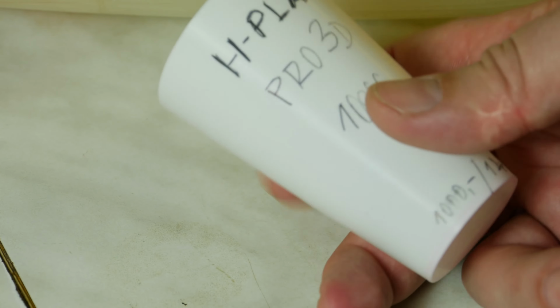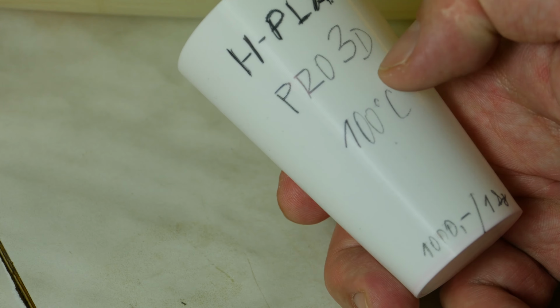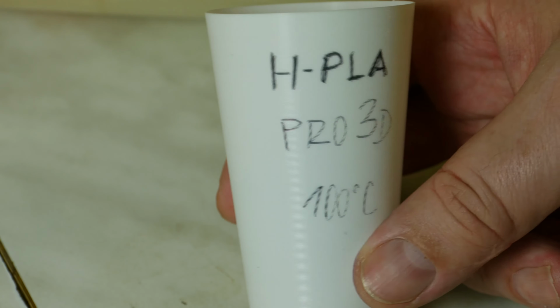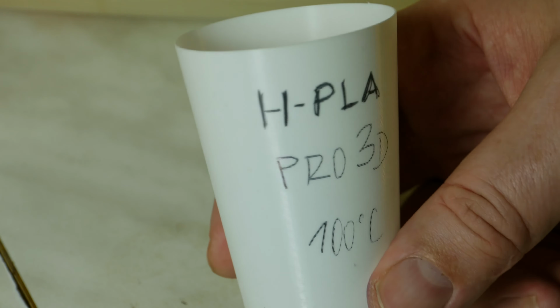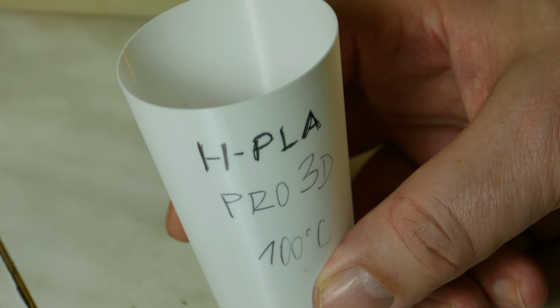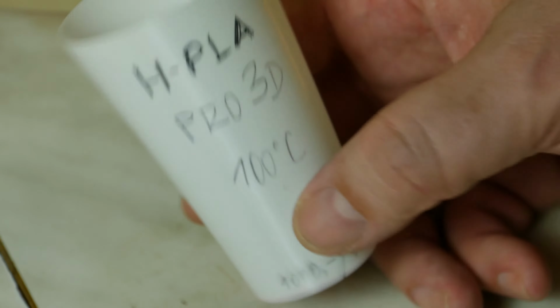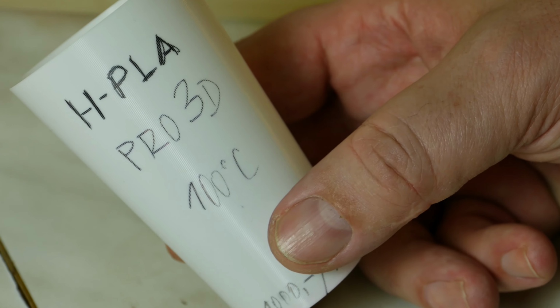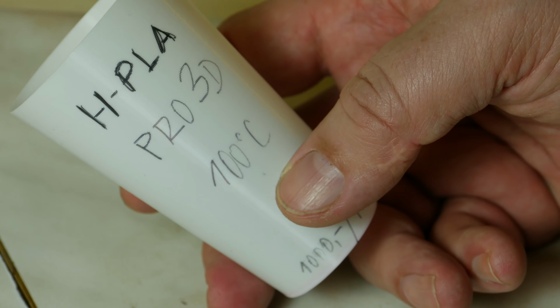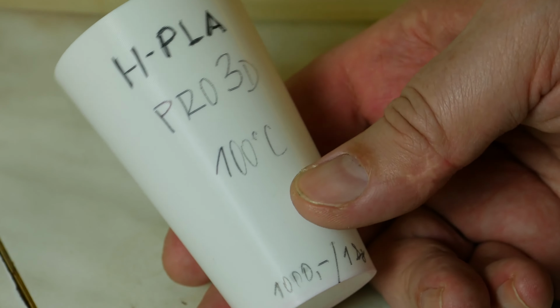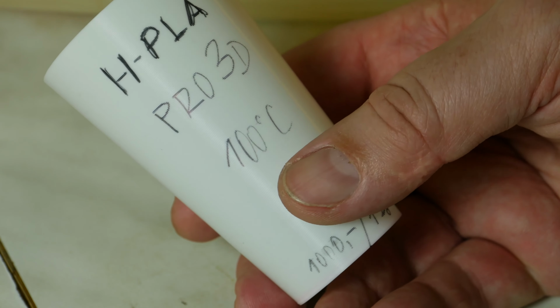Next material is my favorite for most applications, H-PLA by Pro 3D company. This prints for 3D print almost and absolutely the same as normal nice PLA. All temperatures, hot bed, hot end, everything is just the same as normal PLA. But after print, without any annealing, just as it is, you will have temperature resistance of about 100 degrees Celsius. Yes. Standard PLA 50 or 60, H-PLA 100 degrees Celsius.